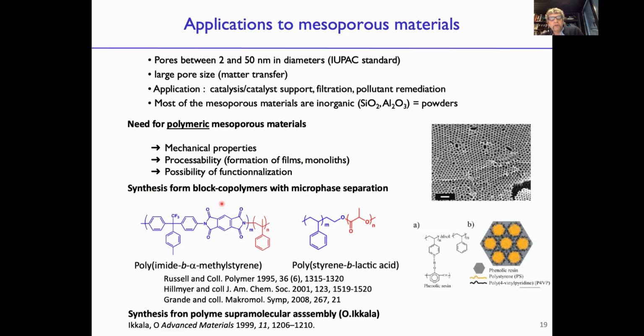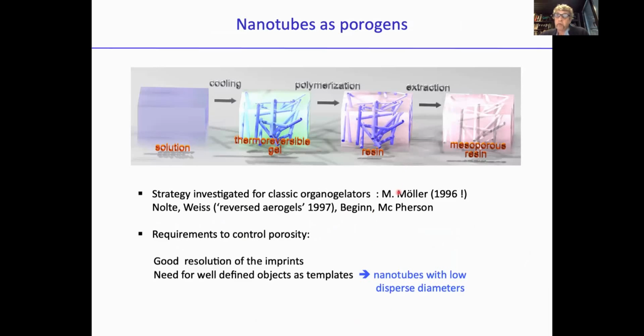There are basically two different strategies. One is using block copolymers, because block copolymers tend to self-assemble into structures that can form cylinders, and one of the parts can be degraded more easily than the other. Another strategy is to use a supramolecular template. It was developed especially by Ikkala, where one of the blocks can be dissociated and leave these pores. And this is pretty much the strategy that we have followed. In fact, this strategy was proposed a long time ago by two different groups, the one of Martin Möller and the other by Dick Weiss, and developed by others.